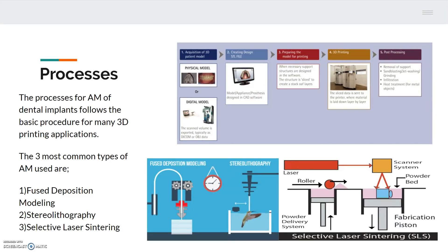The three main types of additive manufacturing used in dental applications are fused deposition modeling, stereolithography, and selective laser sintering. Fused deposition modeling is when a plastic or metal wire is fed through a heated extrusion head and arranged in layers to create a solid part — it is considered a solid-based additive manufacturing technology. Stereolithography is when a solid part is created layer by layer through photopolymerization of liquid monomers, using light to change the structure of liquid molecules into solid polymers. Finally, selective laser sintering uses a laser to bind a powdered material together to form a solid part.